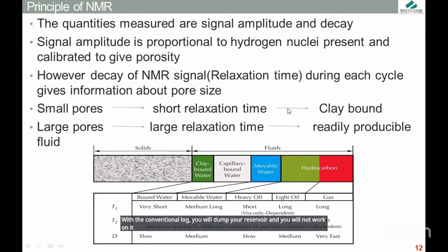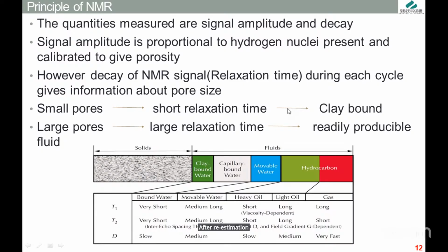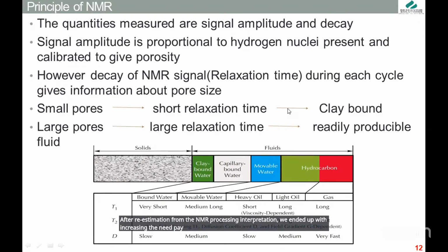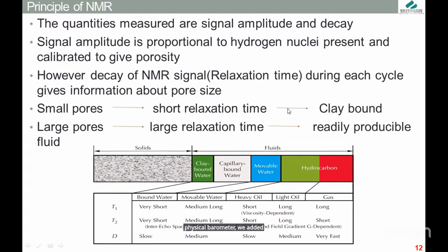Actually, after using the water saturation we estimated from the NMR, after re-estimation from the NMR processing and interpretation, we ended up with an increased net pay, because in some of these intervals the water saturation was below the cutoff. But after running the NMR and re-estimating the petrophysical parameters, we added this zone to the net pay because the water saturation is reduced.